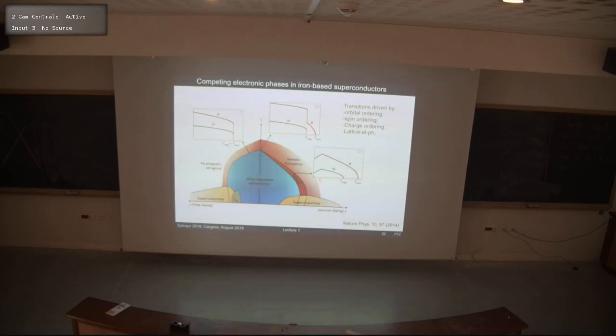As I said, the structural transition is believed to be of electronic origin, and the fact that it breaks rotational symmetry and we have anisotropy in plane is called a nematic transition. If we use electron doping, it's believed that there are even stronger fluctuations above this transition, which are potentially responsible also for superconductivity in the system.